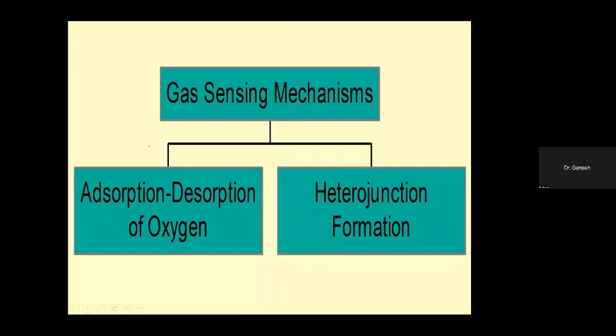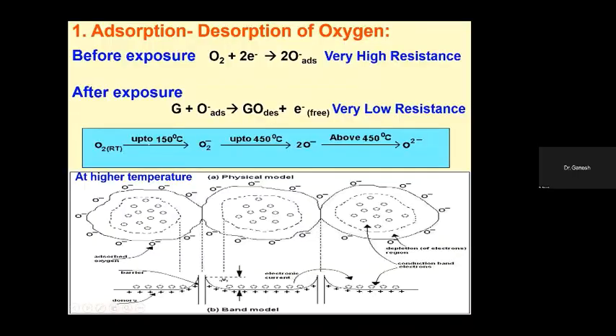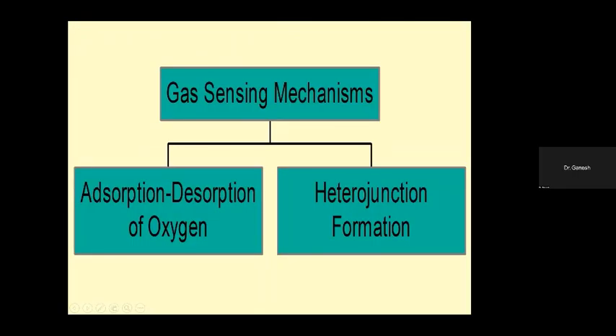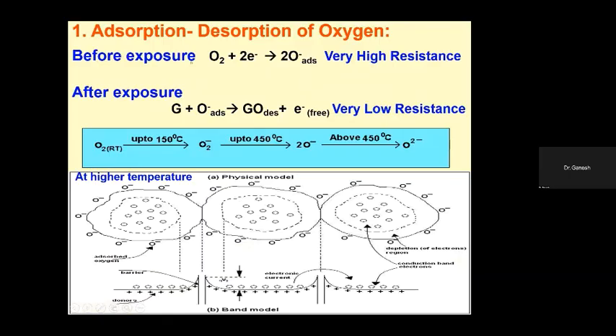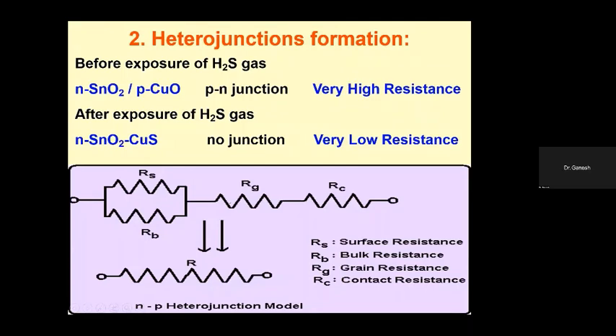Yes, sir. So here we have two gas sensing mechanisms: adsorption and desorption of oxygen, and heterojunction formation. Before exposure to the gas, oxygen can capture 2 electrons from the material, and it becomes 2O minus. These appear on the surface of the sensor, and after exposure, this oxygen liberates the electrons into the material.